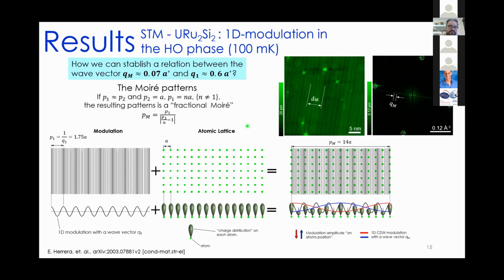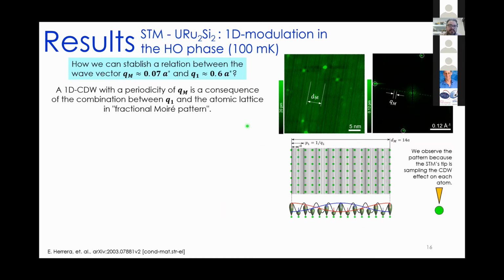So with this, we can say that our images show a one-dimensional charge density wave with a periodicity Qm as a consequence of the combination between the Q1 vector and the atomic lattice in a fractional moiré pattern. So we observe this pattern because the STM tip is sampling this charge density wave effect on each atom. Now that we have the mathematics behind, the next step is to try to identify the physics, the origin of the modulation with this specific vector.